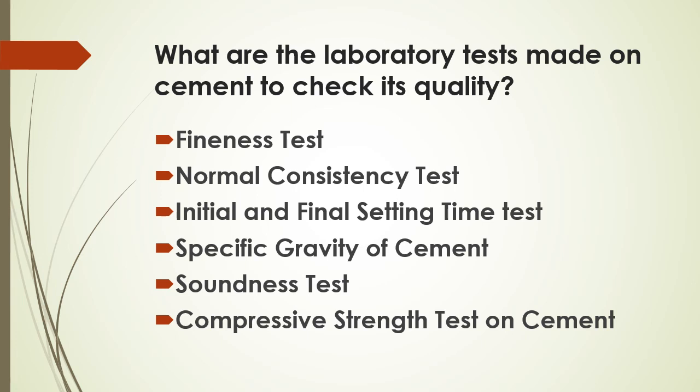Next is the compressive strength test on cement. We cannot test cement alone directly, so we prepare a cement mortar mix of 1:3 — 1 part cement to 3 parts fine aggregate. The water percentage is based on the normal consistency test. Then we go for the compressive strength test.